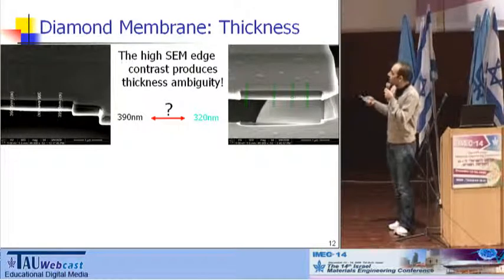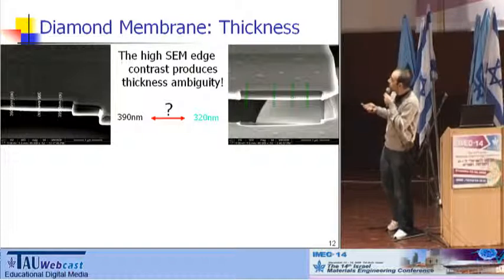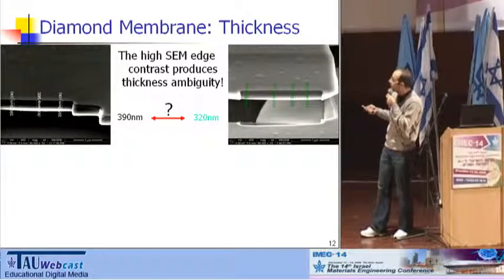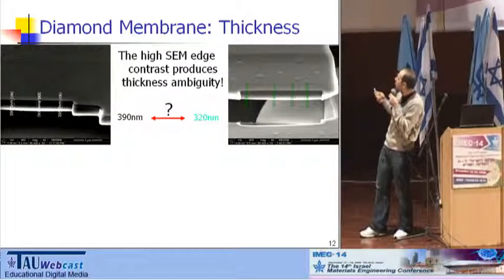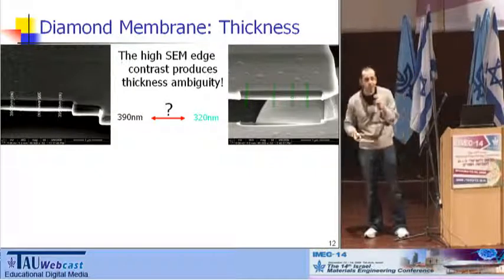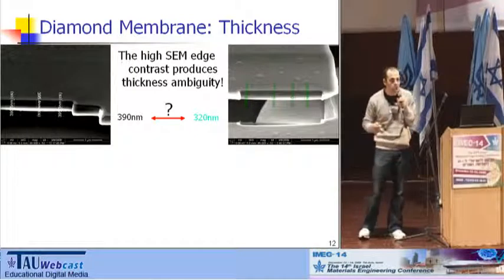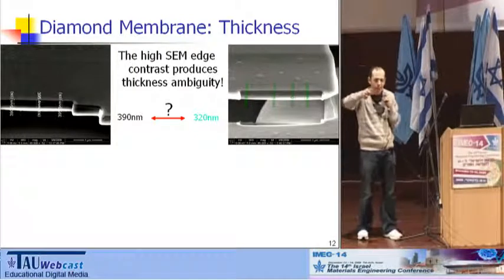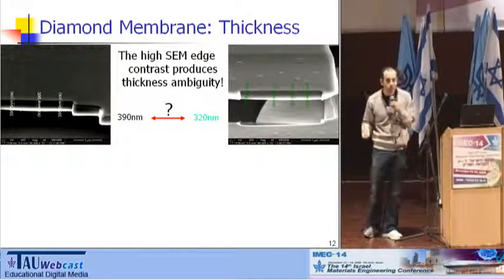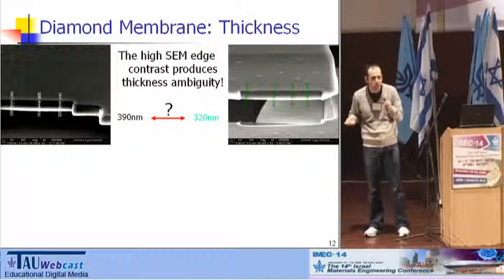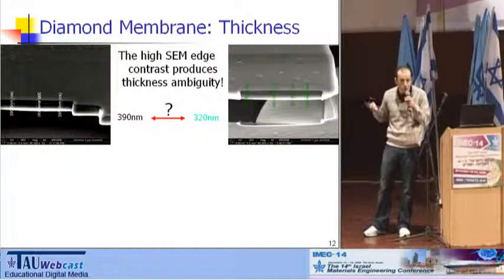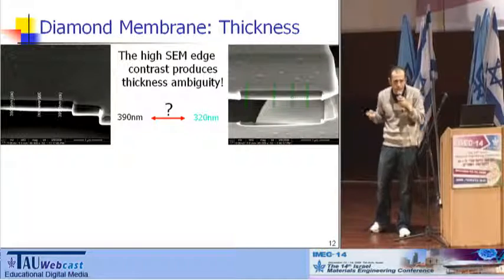So we cut the cross-section, and during the cross-section cut, there is a redeposition of carbon on the lower edge, both here and here. As a result, when you look at this picture in the SEM and you toggle the brightness or the contrast, you can see the ambiguity in the thickness measurement, and this ambiguity can reach 100 nanometer, which is totally unacceptable